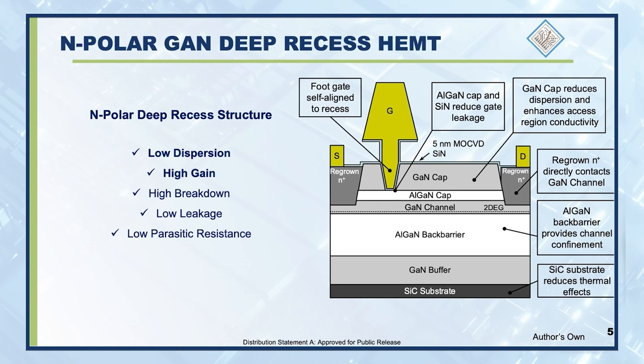we have developed regrown N+, which is highly doped gallium nitride. These regrown regions form the contacts to the two-dimensional electron gas. And these contacts are very high quality, i.e. they have very low resistance.